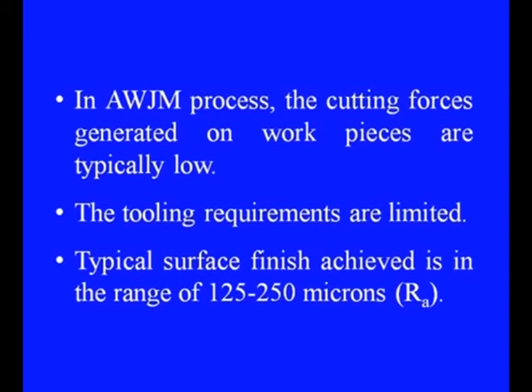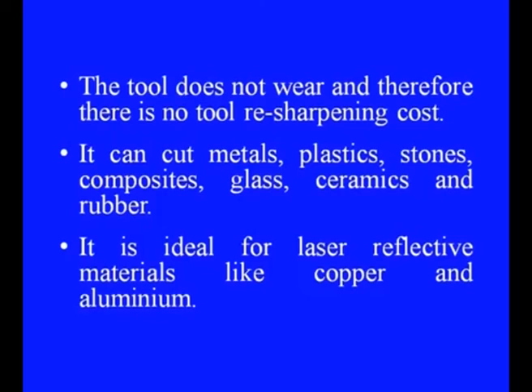In the abrasive water jet machining process, the cutting forces generated on the workpieces are typically very low. The tooling requirements are limited. The typical surface finish achieved is in a range of 125 to 250 microns of average roughness, which we call Ra. The material wastage is reduced due to smaller kerf sizes. There is no cutter induced metallic contamination. The process also eliminates thermal distortions nearby to the cutting zones. The tool does not wear, and therefore there is no tool resharpening cost.